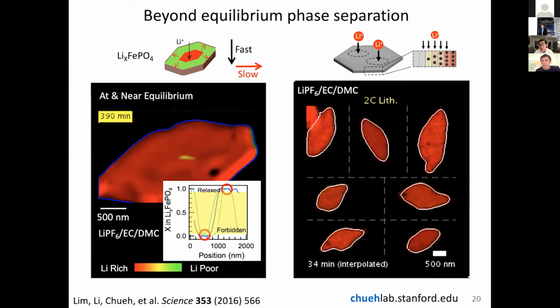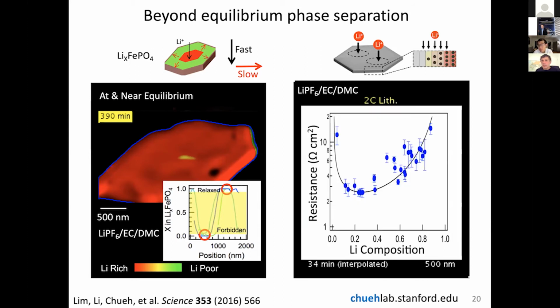So what this means is that we are accessing thermodynamically unstable compositions. Rather than having a phase transformation by forming a phase boundary, you have some sort of metastable solid solution, which means that phase separation is not happening. So what's going on here? This connects back to the concept I was mentioning, which is the autocatalytic effect. It turns out that the resistance of inserting lithium into this material highly depends on how much lithium is in the system.